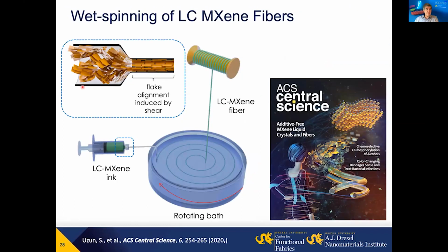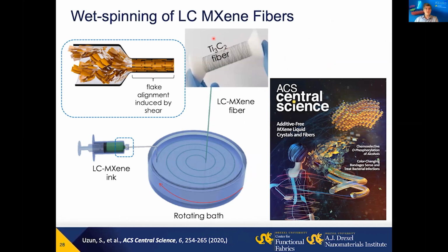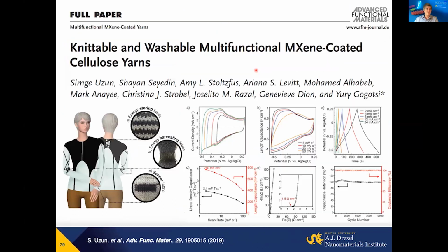And we can take a liquid crystalline suspension of MXene flakes and draw fibers. This is a collaboration with Deakin University in Australia with Joe Razal. It was published also just half a year ago in ACS Central Science, and was on the cover of the journal here, making pure MXene fibers. So there is nothing else, virtually no additives. And you can see an SEM image of this fiber here, and here is a roll with a fiber drawn.